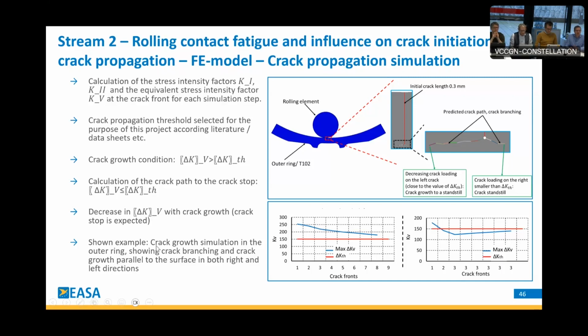Now let's go back to an example here. This example shows the crack growth simulation of the outer ring. It shows crack branching and crack growth parallel to the surface in both right and left directions. So I go back here, I just mentioned it. This is the left side here, the decrease in crack loading on the left track. So close to the value of delta K_th, the crack growth should go to a standstill. On the other side, the crack loading on the right is smaller than delta K_th, so the crack is at a standstill. And these two sides are further shown here in these diagrams. So you see the max delta KV over the delta K_th. Then you will notice that the one is above the red line and the other one is below the red line.